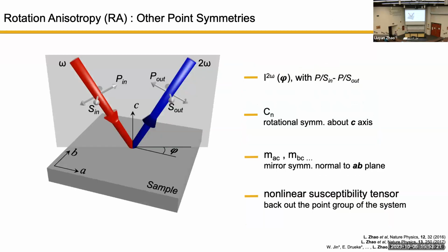In addition to the inversion symmetry, we can design our experiment in this so-called rotation anisotropic way, meaning that I shine light at omega here and get light at 2 omega out, and these two beams form a scattering plane. Then I can choose light polarization to be either normal to this plane, which I call S, or parallel to this plane, which I call P. So I have S and P for both incoming and outgoing, and I will have 4 polarization channels.